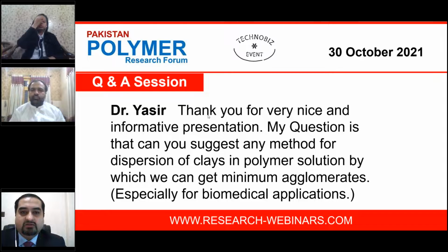The clay layers will try to reassemble once again. So it totally depends upon how you make sure that your polymer solution is dried out properly, by either using centrifugation or trying to get as quick an elimination of the solvent as possible so that your agglomerates don't form once again. If you just leave them overnight to dry, in the end the final product that you achieve will once again show quite a lot of agglomerates. If you have carried out scanning electron microscope analysis of polymers, you are always asked to use as bare a minimum of a sample that has been dispersed in any solvent or any dispersant so that you don't see any agglomerates in the SEM.